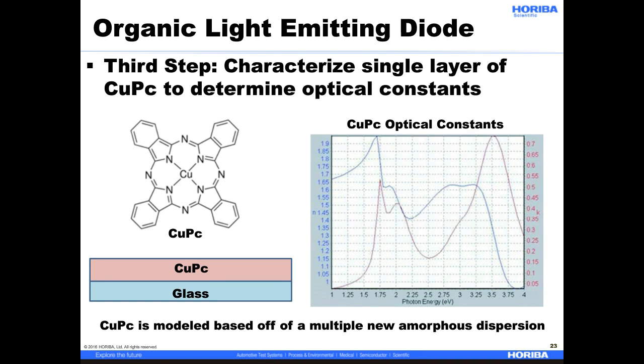The third step here is to characterize the single layer of copper phthalocyanine to determine the optical constants again. Here's the CuPC molecule. This is CuPC on glass, and you have the optical constants of that material. And just like the others - and you'll see a trend here - we can also model this with a multiple new amorphous dispersion function.